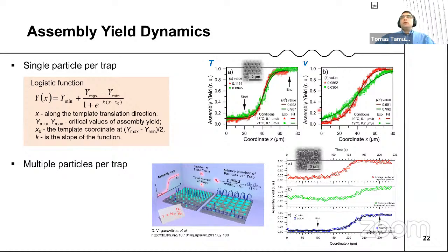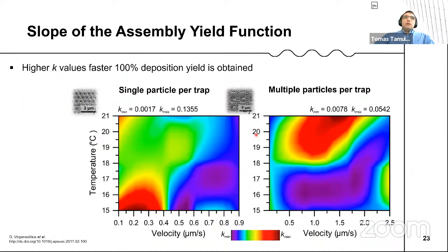And we found that we can control the transition from poor deposition to 100% yield, this switch, by selecting good conditions of the speed and the temperature. We use some sigmoidal functions to describe it. This is the case of a single particle per trap. This is the case of multiple particles per trap. But there is some kind of a space, around 40 micrometers, that is not of good quality when you start to deposit. So you want to make it as small as possible and not have half of your sample partially filled. And it looks like this.